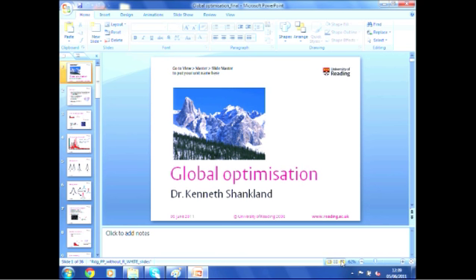Okay, so there are actually multiple little questions wrapped in there. Taking the first one, if you collect your data at room temperature and you have a trial structure from another crystal that was done at 80 Kelvin, it doesn't really have any impact. The bond length and angle changes are minuscule. Next, if you had some ambiguity over a particular form of a group, maybe a cis or trans, try both, simple.